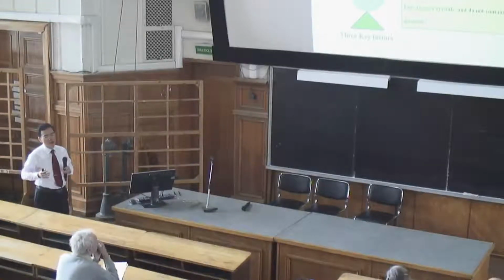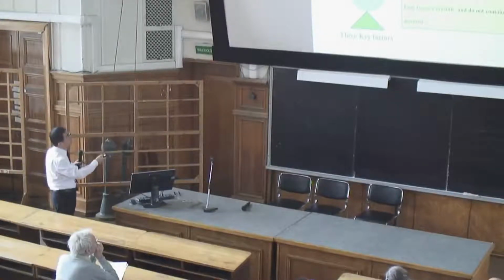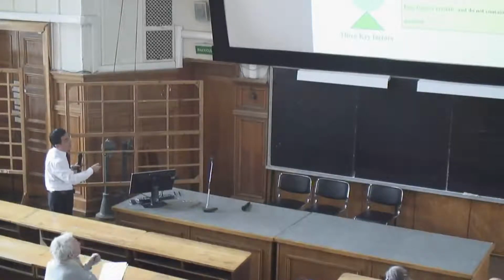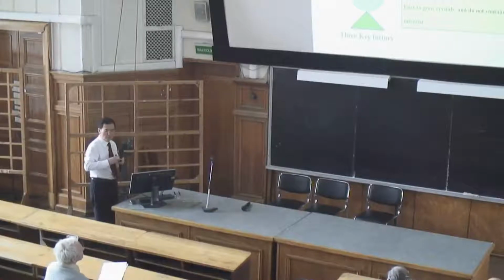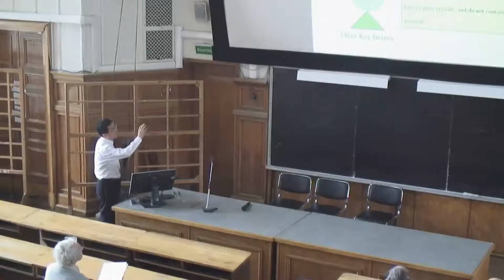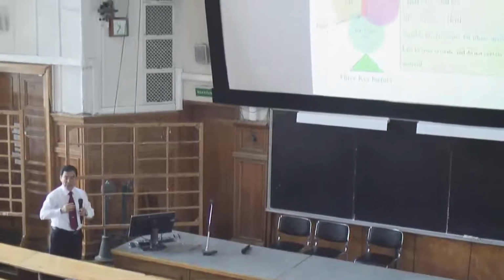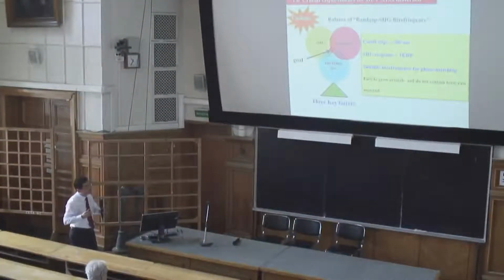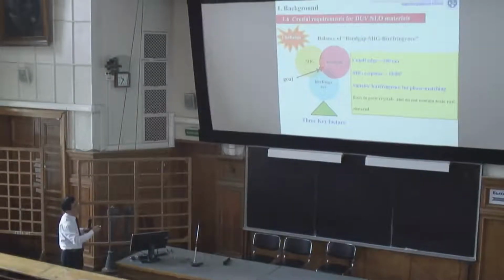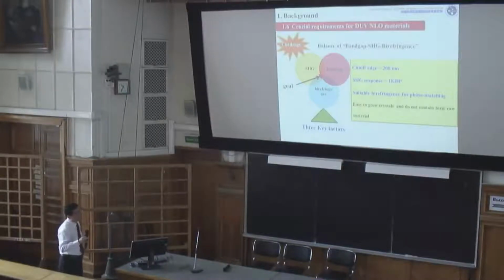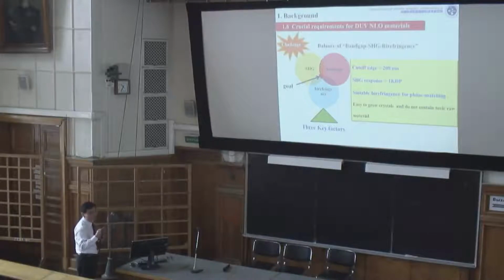However, it's difficult because we should balance the 3 factors among SHG response, birefringence, and band gap. In fact, it's difficult to balance these 3 factors because, for example, band gap and SHG response are inversely proportional. For the UV or deep UV materials, the UV cutoff edge should be less than 200 nanometers. The SHG response should in general be larger than 1 times that of KDP. And those materials should have suitable birefringence for phase matching. Of course, the material should be easy to grow as a crystal and not contain toxic raw materials.